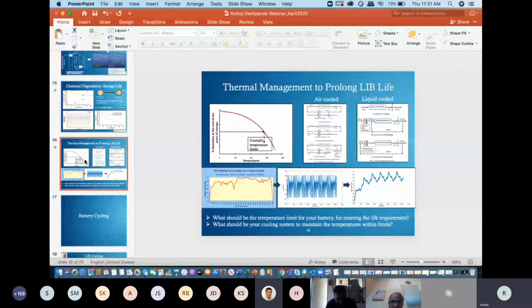Yeah, I have seen specifically a lot of startups. The batteries I'm seeing are totally enclosed, and if you don't have good heat transfer outside, and you are using it at higher rates, then your battery temperature would rise to 55 or more than 55. You definitely don't want to use a battery after 60 because it may go into runaway reactions. That's not safe. So it's important to monitor your temperatures and have a control system which will not allow you to use the battery after a certain temperature.